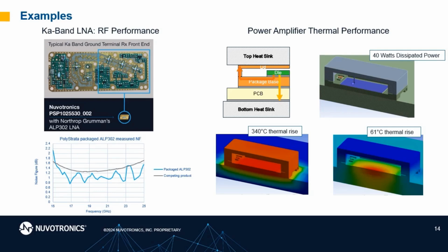Then on the right side, we show exactly the same setup, except we've now removed the heatsink from the bottom of the circuit board and put it on the top of our package. You can see there's a dramatic improvement in the thermal resistance, which is resulting in only a 61-degree temperature rise from the backside of the die.